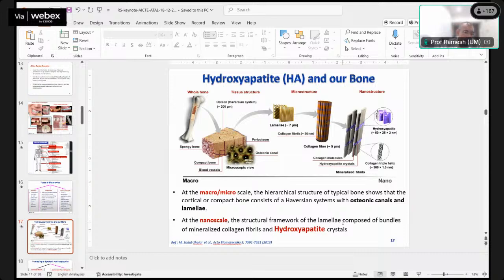And during processing, when we sinter, hydroxyapatite can undergo phase transformation into TCP. So some percentage of the hydroxyapatite crystal can be transformed into TCP, and that becomes an issue if we use hydroxyapatite as a solid implant, because over time, part of this TCP will get leached into the body, get absorbed into the body, and therefore the component loses its mass, and it can fracture.